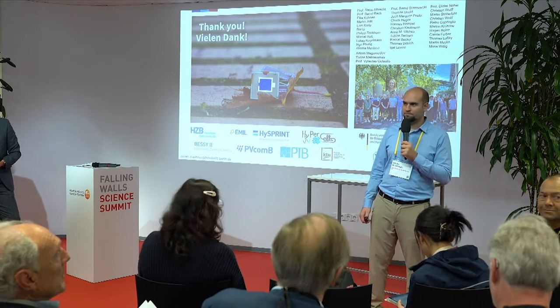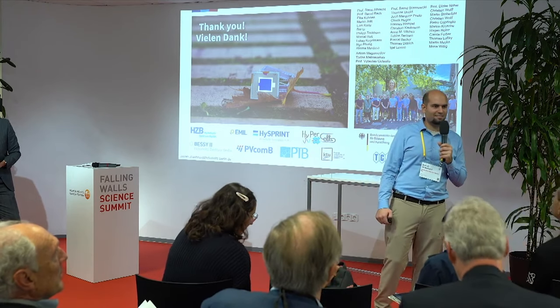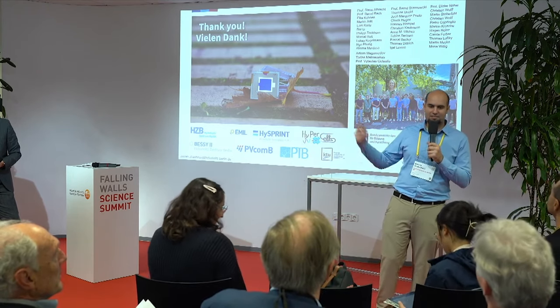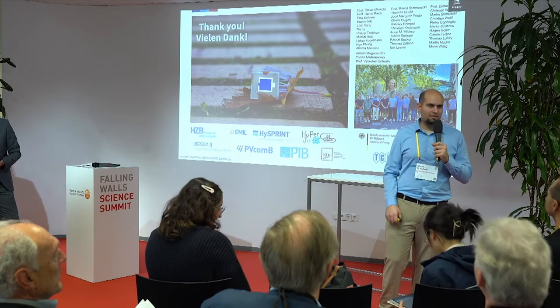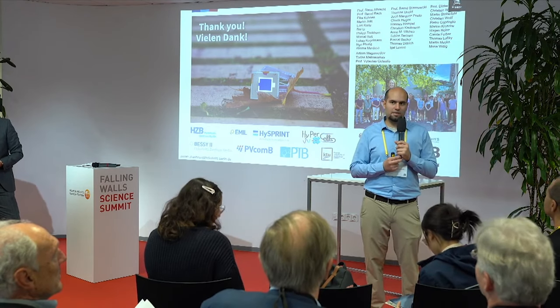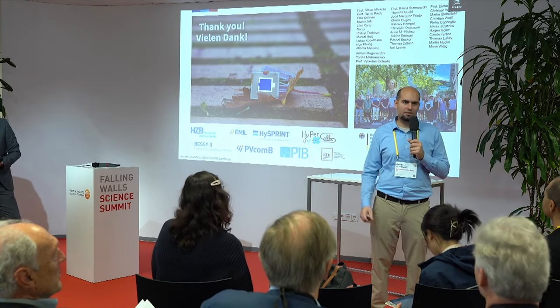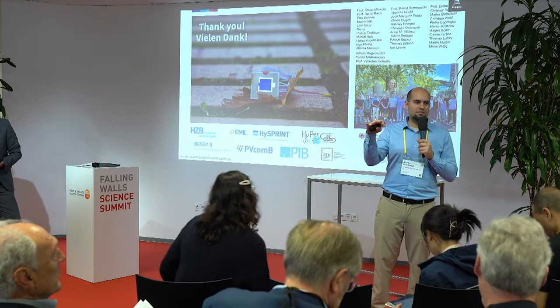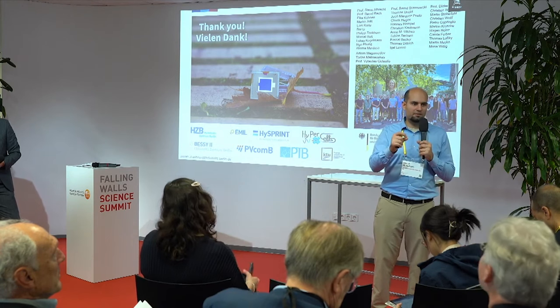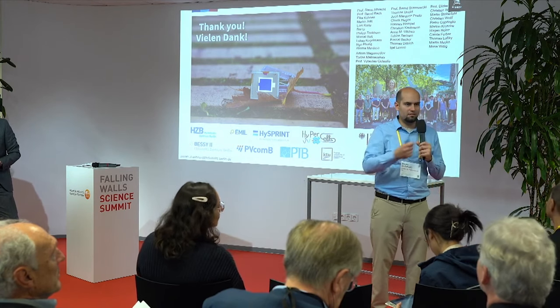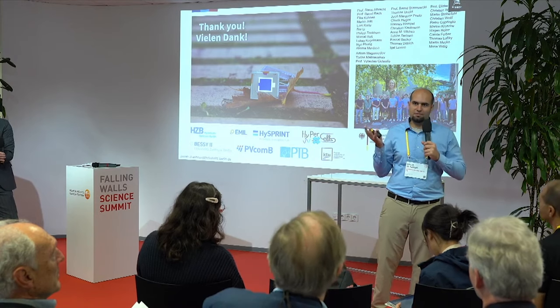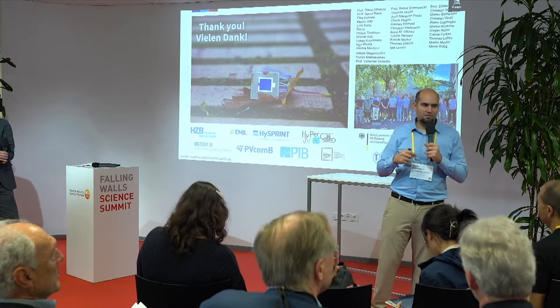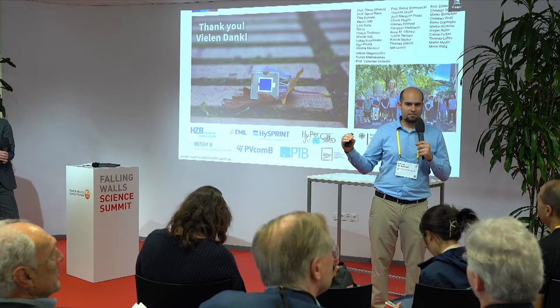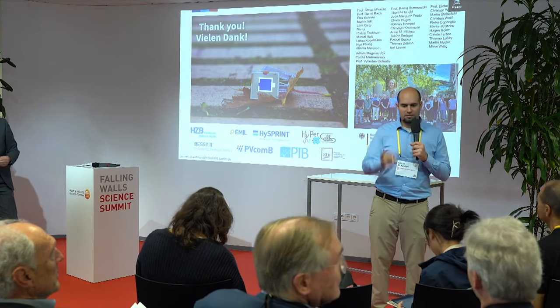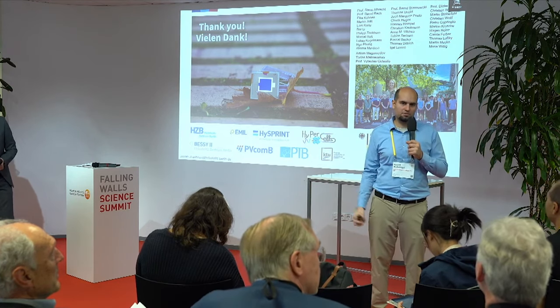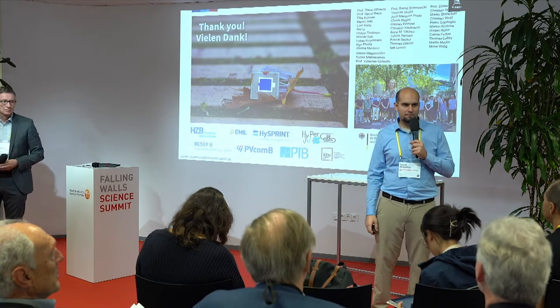So lead, some would say we were gifted with lead, actually, because it gives us these very nice defect-tolerant properties in perovskites. It has not been solved; replacing it remains a real challenge, but there is development in layers that can capture the lead. It's a very, very small amount. If you look at the natural occurrence of lead in the soil, it's roughly similar to what would leak out of the module. But still, you can create organic layers with frameworks that capture the lead as soon as it's soluble. This is, I think, the most promising way.